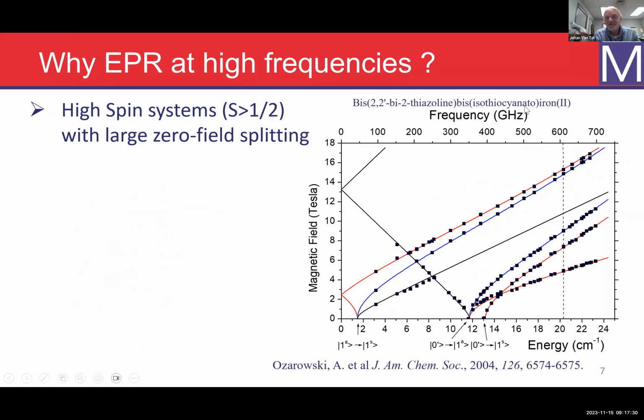So, for example, this is an iron 2+ complex. An iron 2+ at X-band frequencies is typically silent, so you don't see anything for the iron 2+. So if you go to very high frequencies, and this is an example where the magnetic field is on the vertical axis, to change things around a little bit, and the frequency or the energy levels are on the horizontal axis. You'll see that the allowed transitions really occur in zero field at around 350, 400 gigahertz. So you really need the high frequencies.